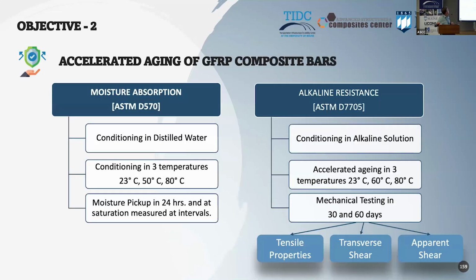Next. Now we look at accelerated aging. This is ongoing. So what I have here is the snapshot of what we have up to today. This is, again, a study that will take longer time. We have data for 30 and 60 days of exposure. We did distilled water. We did at different temperatures. Why at different temperatures? When we increase the temperature, we accelerate the moisture pickup. And by having different temperatures, we can use predictive models like time temperature superposition, because we also have different times.